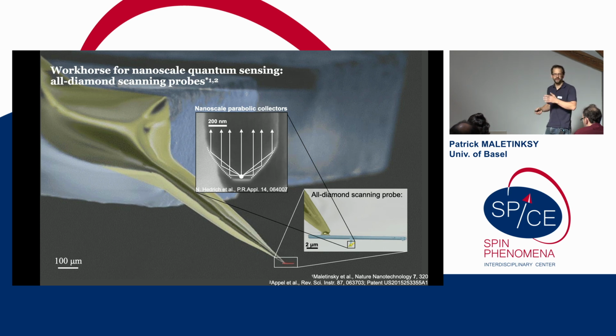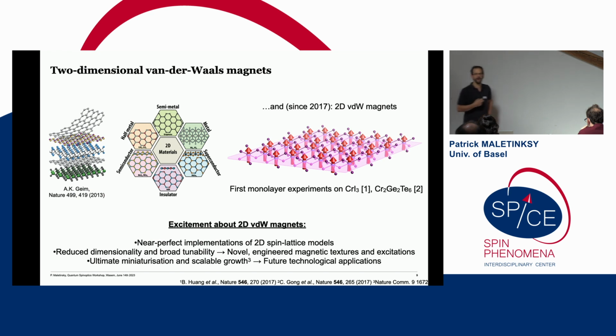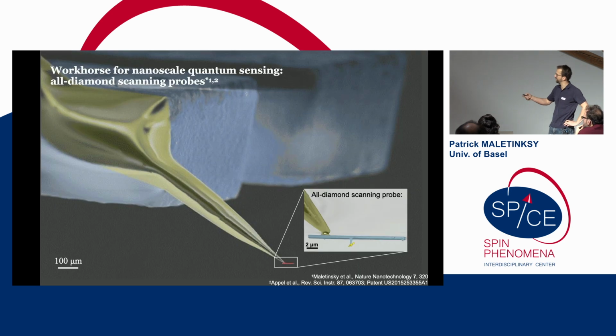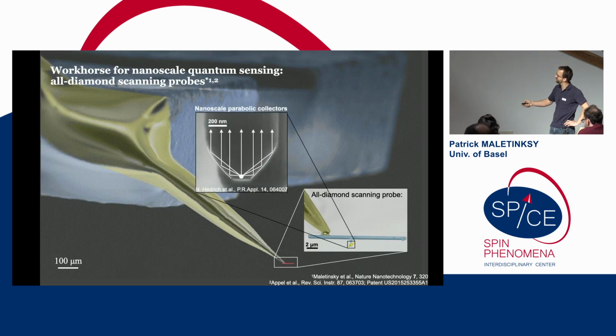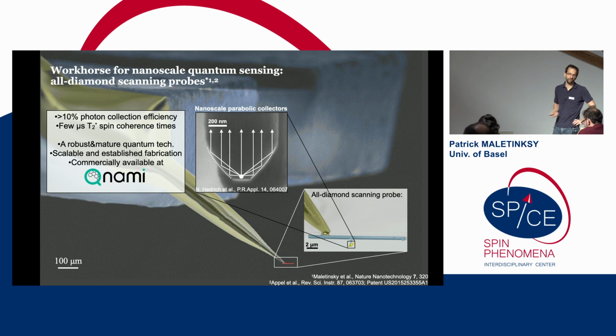The simple understanding here, which is an oversimplified picture, of course, is in a ray picture, you see this parabolic shape that just leads to this, and we're trying to place the NV here in the focus of the parabola, so you get this emission upward. If you analyze the performance of this, we realize today with these scanning probes collection efficiencies from the NV to the detector of roughly 12%. That's a number we're quite happy with, and that leads to those sensitivities that I mentioned before. So all of this is by now quite established in my group.